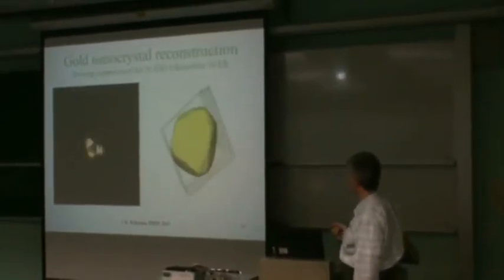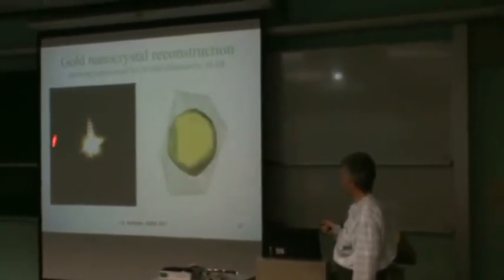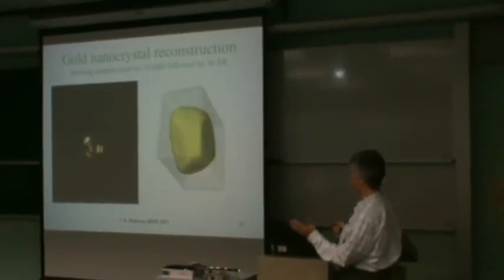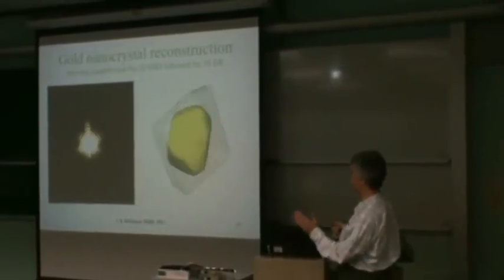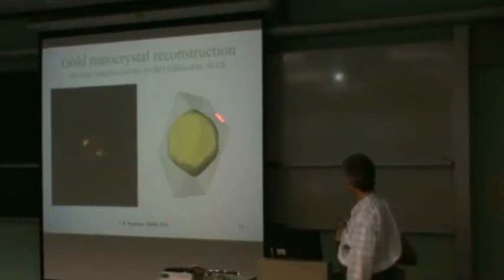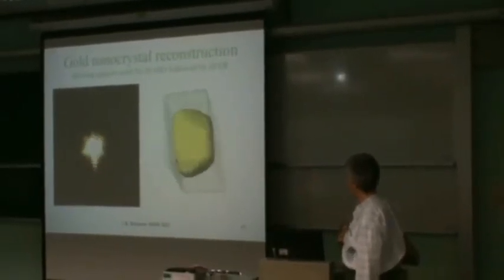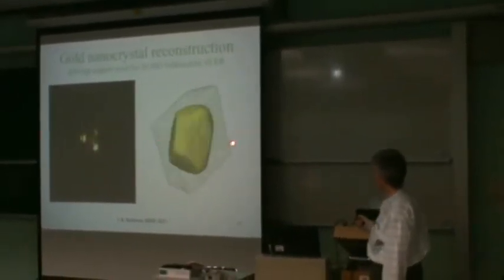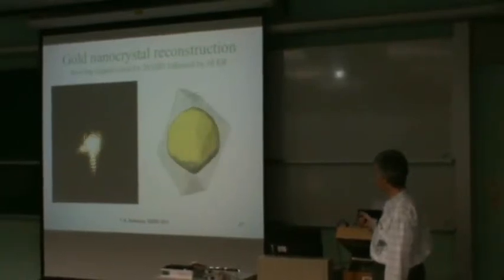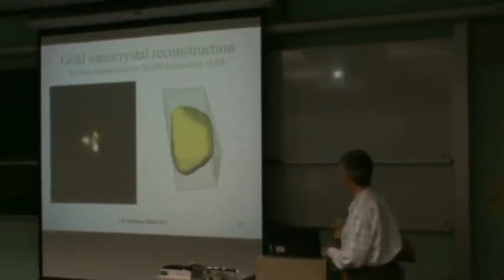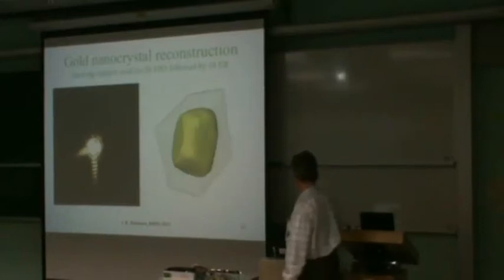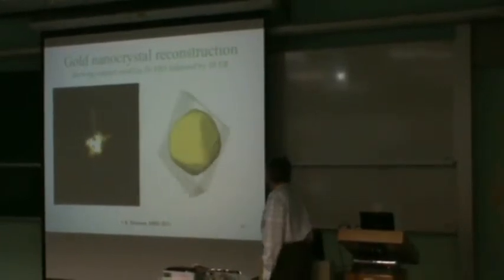This is a gold crystal. The diffraction pattern is again shown as a movie. This corresponds to a rocking curve, rocking the crystal by about 1 degree, and this shows an image of the gold crystal that comes out. This is about 200 nanometers across, and you can see it's got this nice faceted shape that is the growth shape of the gold crystal.